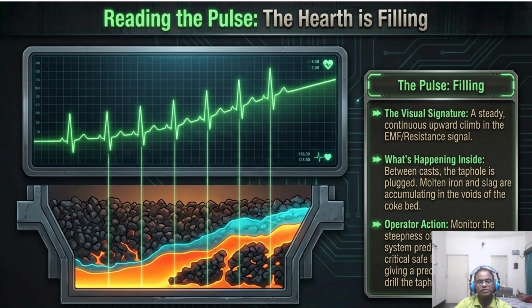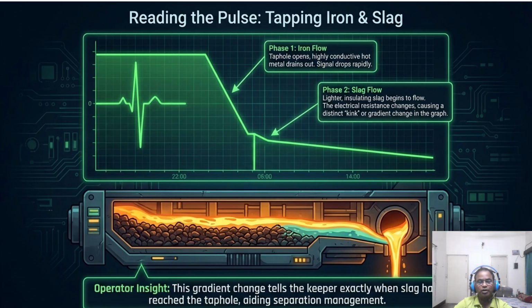Now what happens when you actually start the tap? When the tap hole opens, the signal drops rapidly, and this is phase 1, the iron flow. So notice this distinct kink or gradient change. That tells the keeper exactly when the lighter insulating slag has reached the tap hole. If the signal gradient is lower than usual, it's a warning that the tap hole might be choked by blockages or not siphoning from the right point, or there is any short circuiting, and you might need to close and redrill, or follow whatever philosophy is being exercised in that shop on that cast floor. So this helps us manage slag separation with pinpoint accuracy.